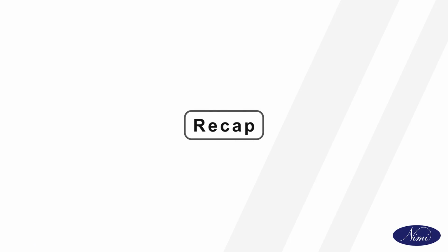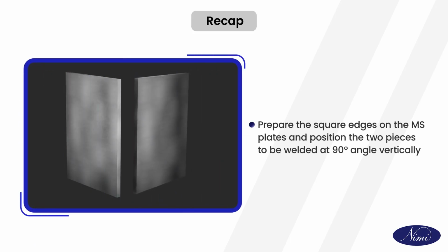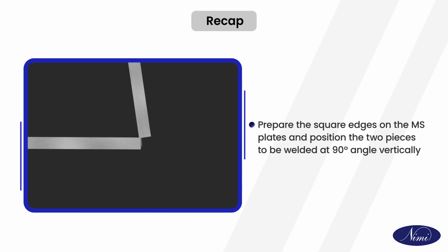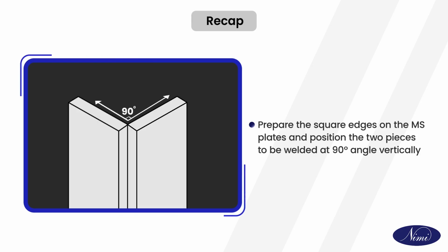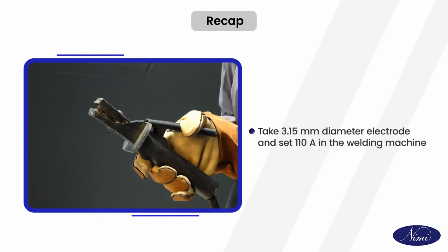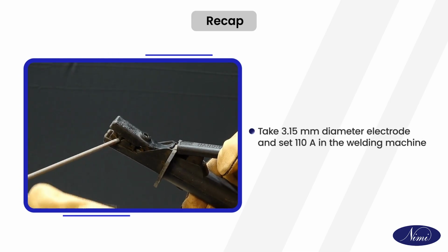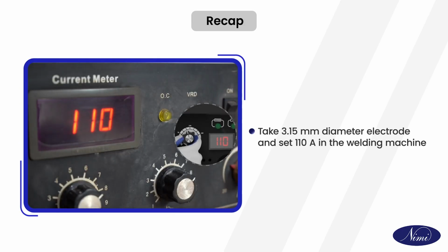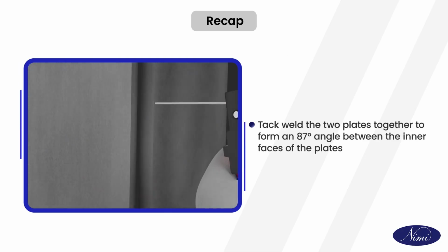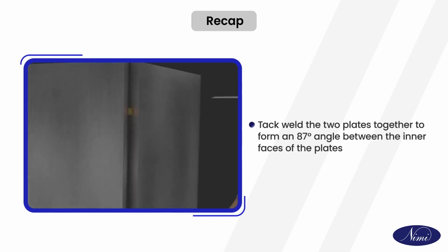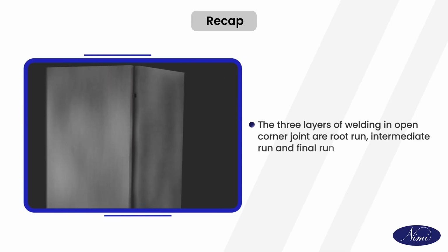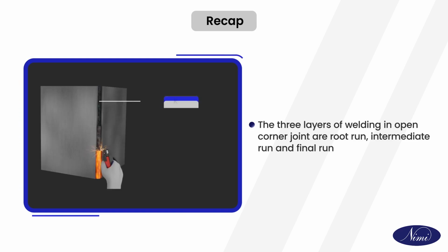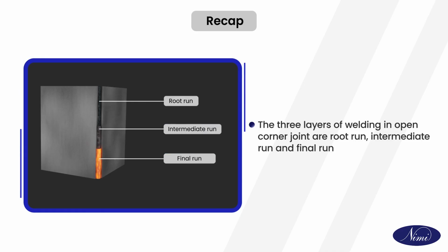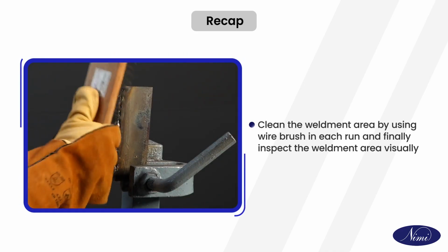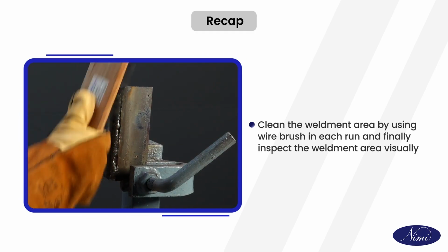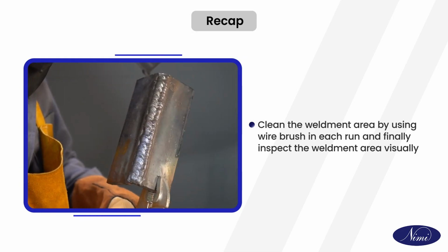Let's recap the key points discussed. Prepare the square edges on the mild steel plates and position the two pieces to be welded at 90-degree angle vertically. Take 3.15 mm diameter electrode and set 110 ampere in the welding machine. Tack weld the two plates together to form an 87-degree angle between the inner faces of the plates. The three layers of welding in open corner joint are root run, intermediate run, and final run. Clean the weldment area by using wire brush in each run and finally inspect the weldment area visually.